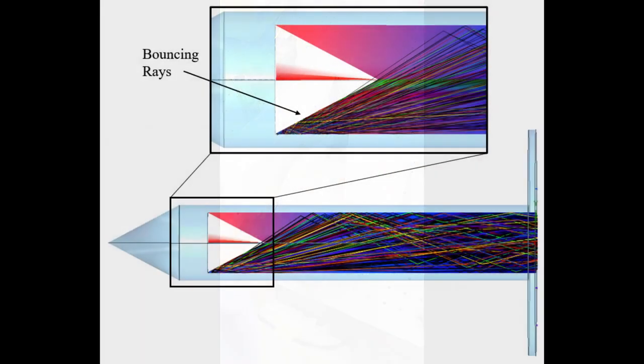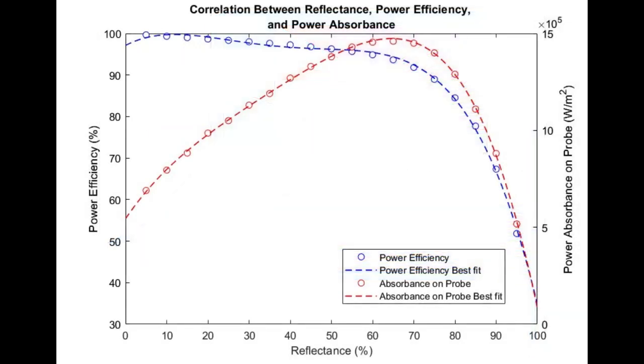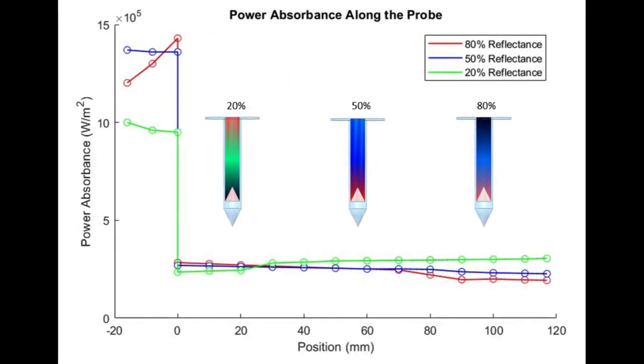These simulations validated that even with tungsten's typical reflectance range of 50 to 65%, the probe geometry traps over 94% of provided solar energy by reflecting rays downward towards the probe tip for further absorption. The geometry also ensured that the majority of heat flow was concentrated at the bottom of the tungsten probe for more effective conduction to the liquefying feedstock.